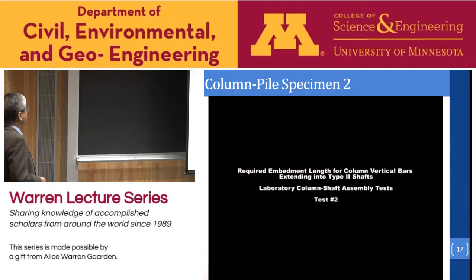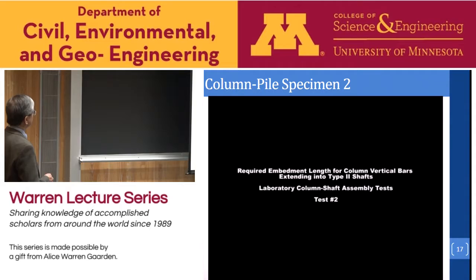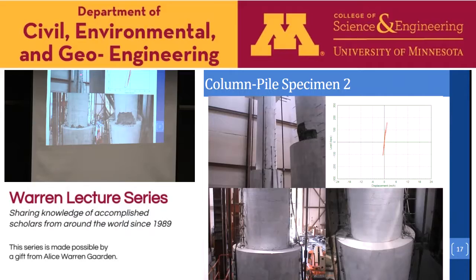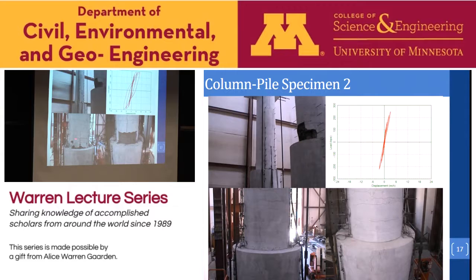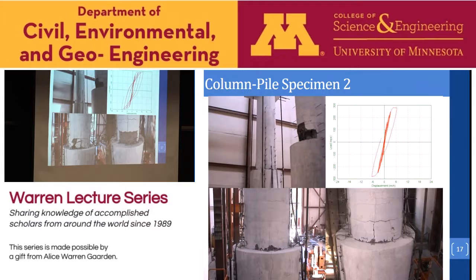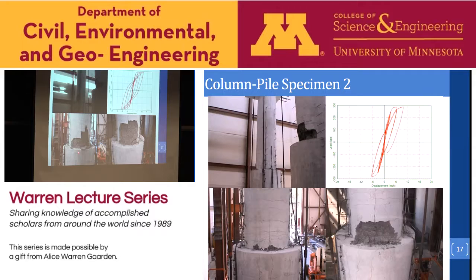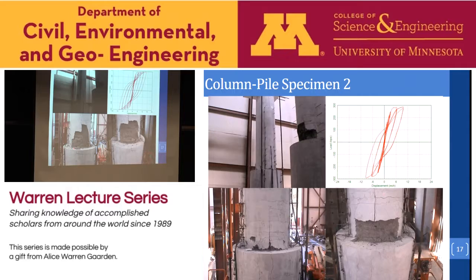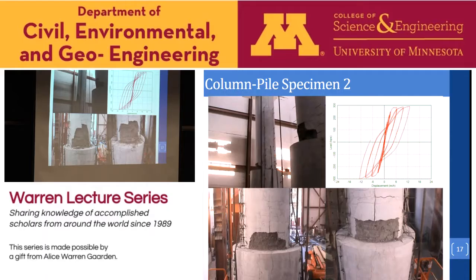The whole purpose, of course, is that we want to have sufficient development length so the plastic hinge will be concentrated at the base of the column with minimum damage in the shaft. And you can see that it indeed achieved that purpose. We have severe crushing of the concrete and buckling of those longitudinal reinforcements. However, we also now start to see cracks developing in the shaft. You see these longitudinal cracks. Those are the tensile splitting cracks because of the bar slip. But these cracks were controlled by the confining steel, the hoops inside the shaft.